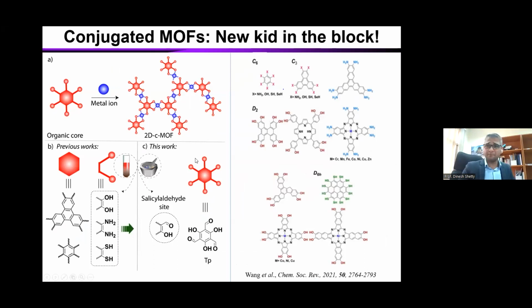And then the last story for this talk from my group. I talked about the COFs, for CO2, for 3D COFs, 2D COFs. But now I'm talking about something called MOFs, but very specific MOFs, the conjugated MOFs. There are different reports using symmetrical molecules to make conjugated MOF systems. But we introduced a kind of no symmetry here. We have a carbonyl and a hydroxy group, and also we used mechanochemistry instead of classical solvothermal chemistry.